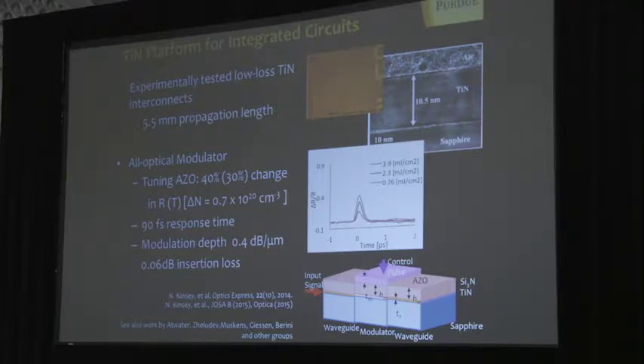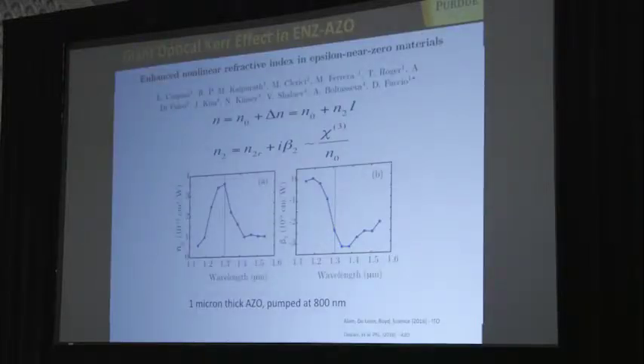Based on the results we measured here, you could see that we changed the reflection coefficient by about 40%. It's a huge change. Transmittance changed by about 30%, and the response time is around 100 femtoseconds. So what we showed is that modulation depths could be quite good, 0.4 dB per micron, which is indeed a very impressive number, at very low insertion loss. All right, this is the result which I think shows the beauty of these ENZ materials.